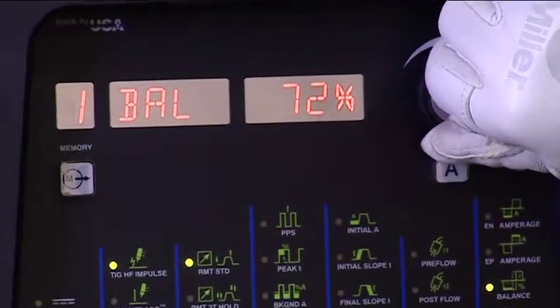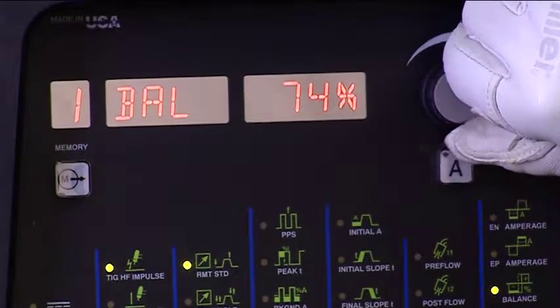Now, we've covered the basic guidelines for setting your balance control. You'll probably find that the optimum setting is in the neighborhood of 65 to 75%. Don't be concerned about this. You'll likely find a sweet spot that works well for most applications and requires very little adjustment. The range of adjustment provides flexibility for advanced applications in extreme conditions. I hope this information about AC balance control helps you get the results you're looking for.